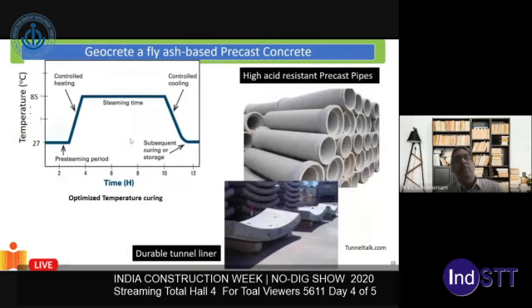So now this is fly ash that's being produced across the country, mostly in rural settings. We are now looking to see if this material could be used to support infrastructure development. Steam curing can easily be adopted, and it is being done for producing a lot of construction related products. If you look at steam curing that is conventionally followed, we raise the temperature to about 85 degrees Celsius, hold it there for some time, 6, 8 to 10 hours, and then we cool down the product.